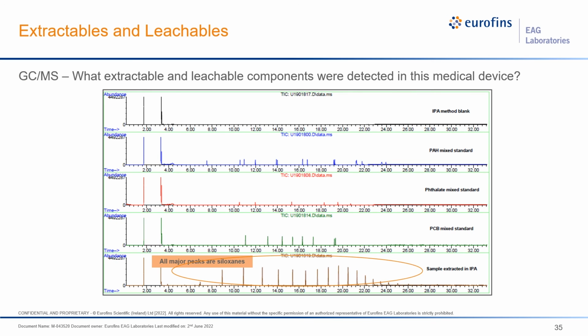So taking a look at some of the chromatograms from our IPA extract of this medical device, on the top we have our method blank, followed by our aromatic hydrocarbon standard, our phthalate standard, our PCB standard, and then finally our sample extract. We don't have time to go through all the data, but the takeaway message here is we looked at all these different peaks and we're able to assign most of them to siloxane-related species, which again, after our first two case studies, we can determine that this comes from the soft part of the medical device.